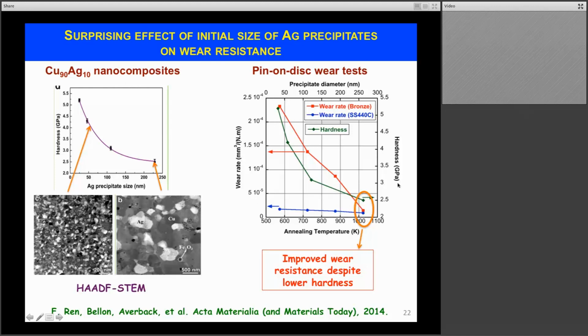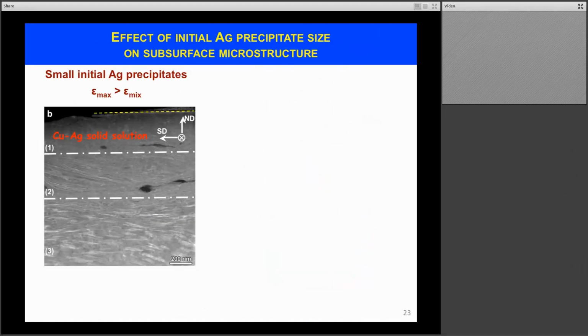But at the same time, these are materials for which the hardness, in green here, is the lowest. And so this material has the best wear resistance, despite the fact that it does not have the highest hardness. And so we looked at the microstructure of these materials to understand why this may have happened.